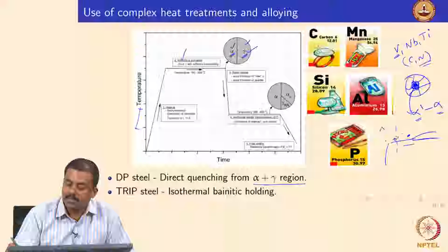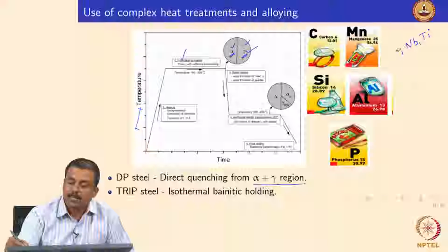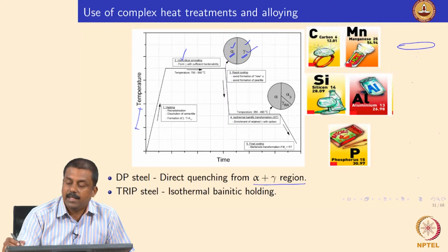So, what is bainite again? Bainite is a mixture of ferrite and cementite in a different morphology than pearlite, right. We can have either upper bainite or lower bainite. In upper bainite, a ferrite lath forms and the carbon subsequently migrates to the adjoining regions of this ferrite lath, and you end up forming cementite at the interlath regions between the ferrite laths. So, we will have ferrite and this is cementite. The upper bainite microstructure typically looks like this.